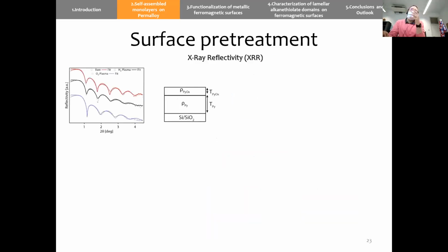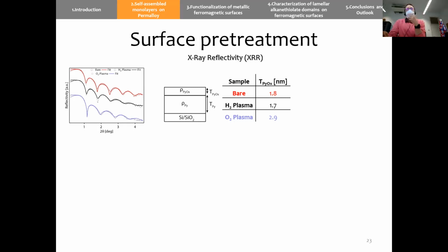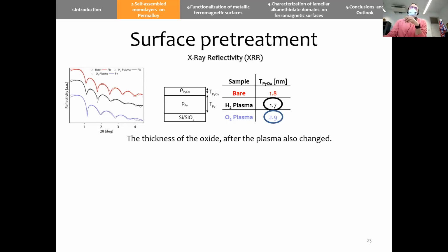We also wanted to understand and study the thickness of the oxide after these treatments. So we used X-ray reflectivity, which is a complementary technique to ellipsometry, and it can be used to model thickness and densities of the material. And also, from a qualitative point of view, by counting the number of fringes, we can have an idea if we are increasing or decreasing the thickness of the material we are working with.